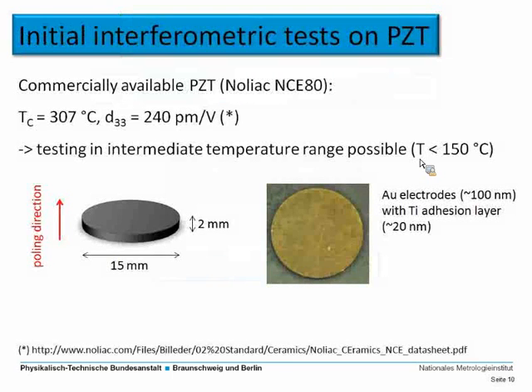For those first tests, we decided just to use a commercial flavor of PZT, in this case Noliac NCE80. We just thought that's easily available, it's not too expensive, we can play around with it, and if we break one, then it doesn't really matter. As supplied by Noliac, the Curie temperature is roughly 300 degrees centigrade. The D33, the piezoelectric coefficient we're interested in here, has a reasonable value, so testing in the intermediate temperature range should be possible, let's say below 150 degrees centigrade.